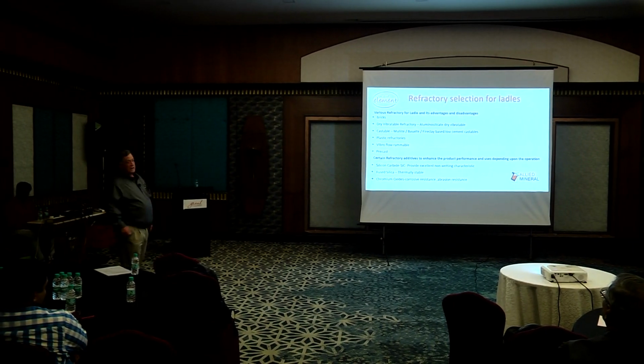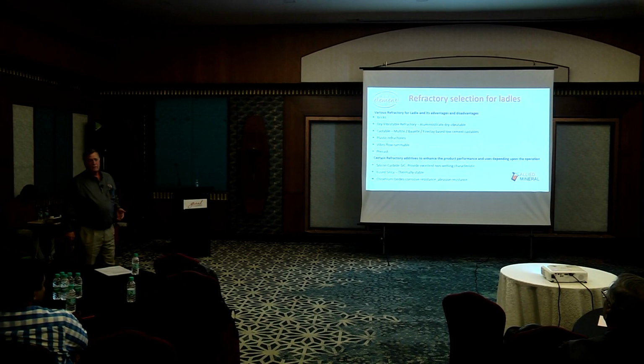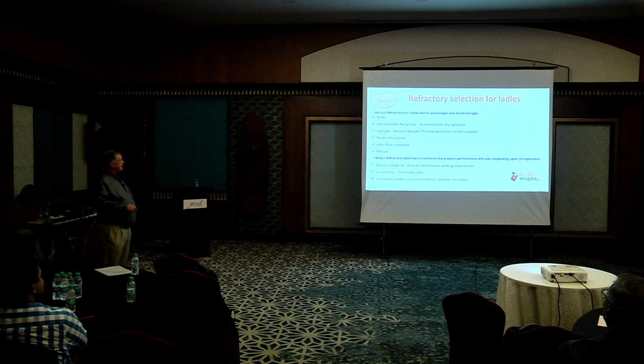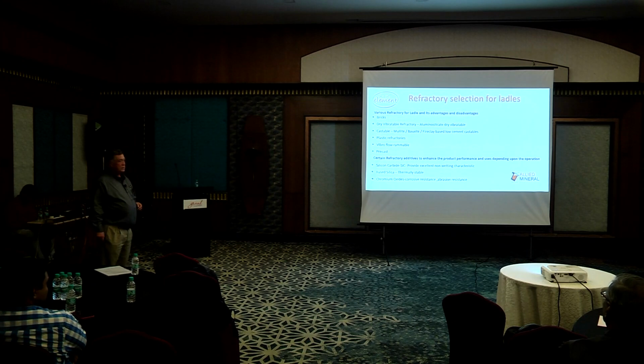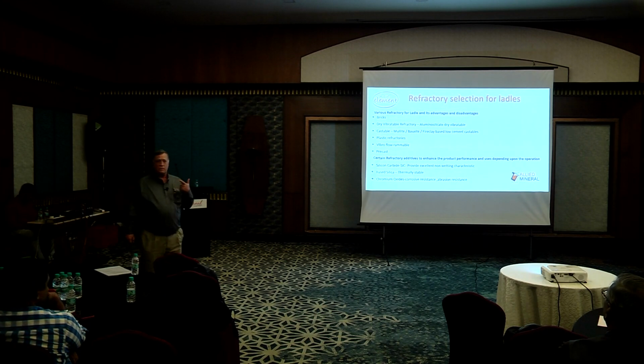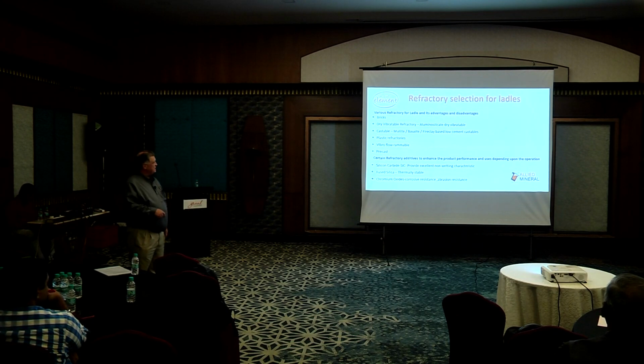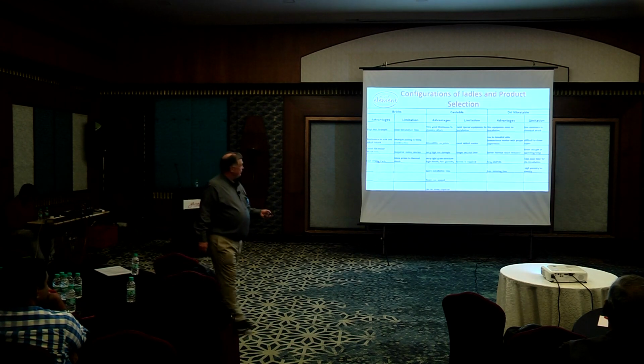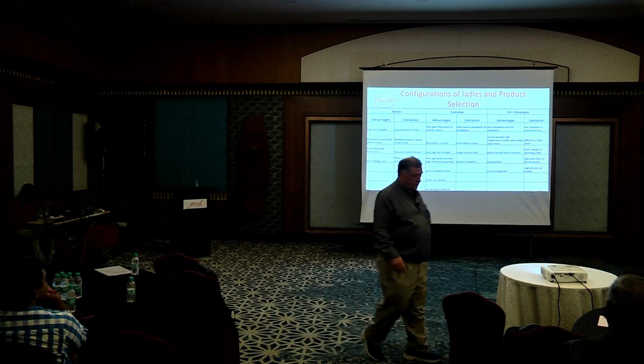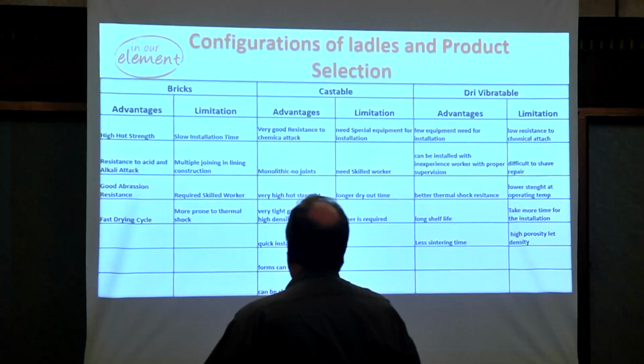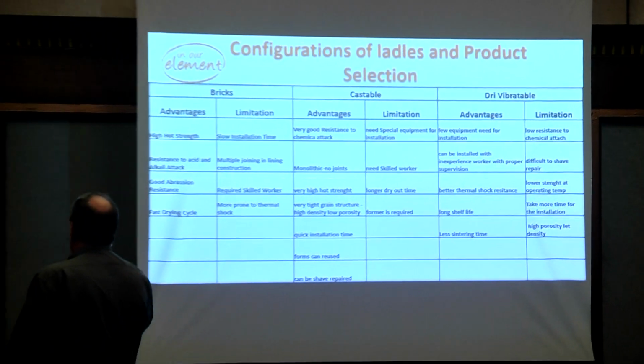If you thermocycle the ladle often, you can put fused silica in the castable to help stabilize the thermal shock and reduce cracking. If you have problems with strength of the castables, with buildup, with corrosion and abrasion resistance, chrome oxide is a really good additive that you can use in ladles to help increase the lining life and reduce problems. Now, bricks: advantages and disadvantages.